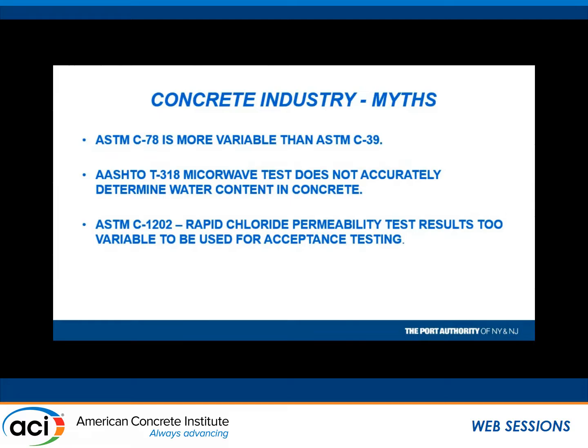Okay, some myths in the industry, I think, is that, you know, the C78 test has a lot of variability, not by our testing, unless we're making up numbers, that the AASHTO T318 test is not good. Well, I beg to differ with you. I don't understand how we can be rebuilding our transportation infrastructure and never testing for water content. If you look at 318, durability is tied to water. How do we do this without testing for water? I don't get it. Maybe somebody can explain it to me.